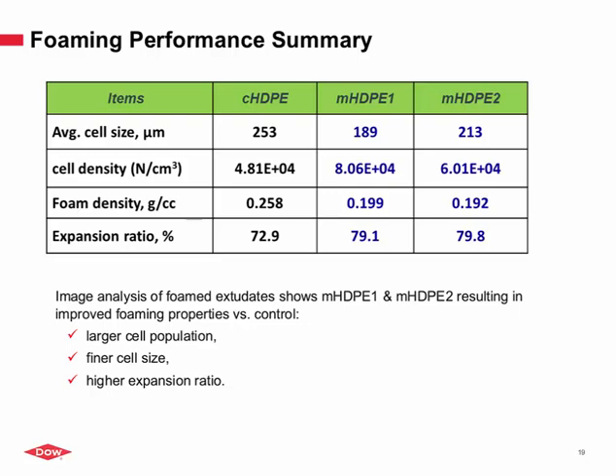To summarize the foaming performance itself, for average cell size, both systems show a clear difference from the control. The expansion ratio as well, which is important, is about 73%. These were all extruded under the same processing conditions, so we are comparing compound differences. Both compounds are showing a much higher level of foaming compared to the control. So we have a larger cell population, finer cell size on average, and a higher expansion ratio.